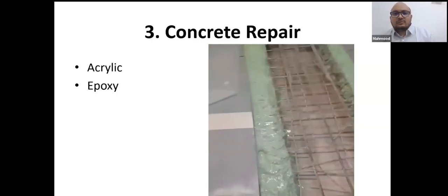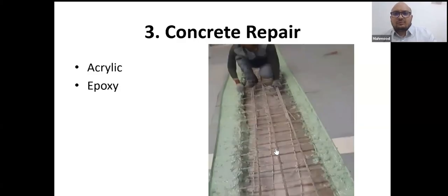After 1 hour, 2 hours, you might have come across this epoxy behavior, the pot life. After mixing, you will have a pot life, usually like 20 minutes. But as per the site condition, you can alter the hardener. For commercial purposes, usually they need 3 hours, 4 hours for preparing formwork. So they supply various tailored products like fast setting and normal setting. Fast setting will become tacky within 1 hour, whereas normal setting will become tacky after 4 hours.